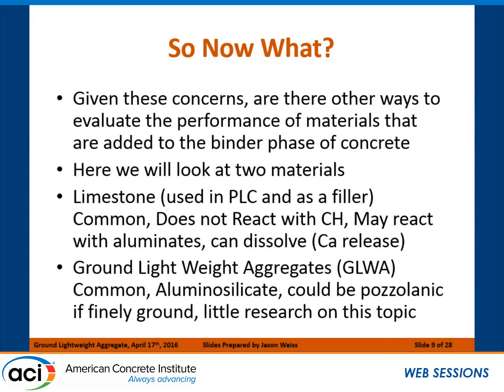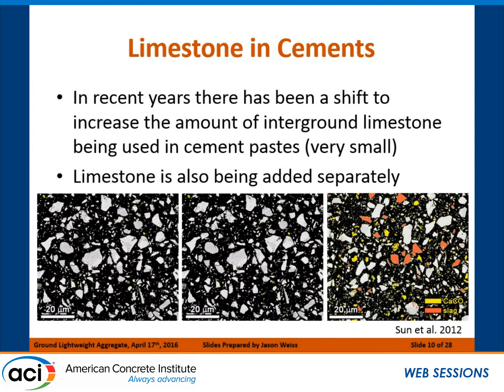And then we also wanted to look at ground lightweight aggregates. And one of the reasons we're looking at ground lightweight aggregates is we hear people saying we don't have enough fly ash and we need the effect of that supplemental material. We can't get consistent fly ash, so this is a question of, is there a possible other source out there? So the ground lightweight aggregates are essentially common. The smallest pieces of this, or the powders of this, the dust of this, is something that's readily available. It's an aluminosilicate, and it can be pozzolanic if it's ground to the right size. And this is really what we wanted to start looking at.